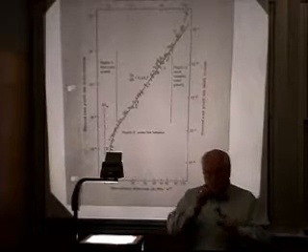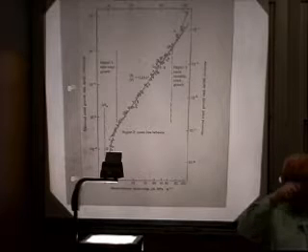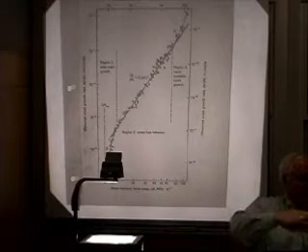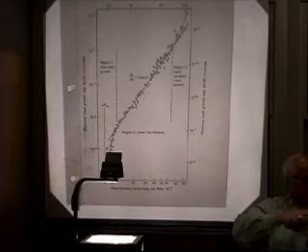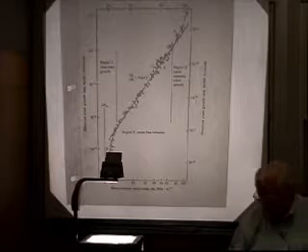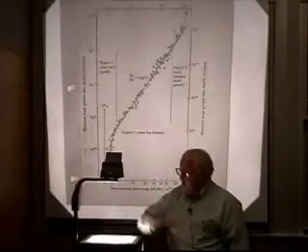But I can generate this curve in about 2 weeks in the machine, because what I'm plotting here is the change in crack length a per cycle. And so I have some little sensor, and sometimes the sensor is nothing more than a little microscope and a light behind it, and I try to measure the crack length as it's moving across. I can also measure the crack opening, because as the crack gets wider, deeper, it opens more and more. So another thing, people use electrical on metals. They use electrical resistance through the thing. They pass a current every now and then, and the cross section that remains has got a higher resistance than if it was a larger cross section. So you use electrical potential drop. You measure the crack growth rate per cycle, and you plot da/dN versus stress intensity, and you get this type of crack growth rate curve.